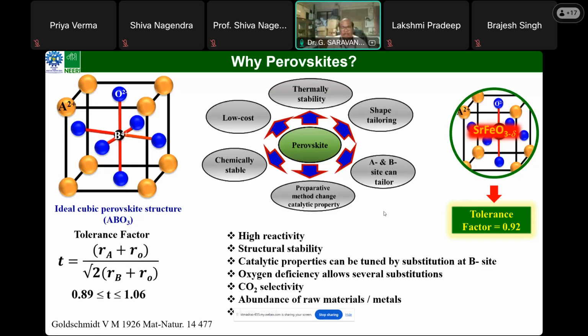to use perovskites for automobile exhaust applications, and it has quite some merit. It is quite stable because the phase formation temperature is generally above 800 degrees. You can play with the shape, you can tailor the A and B sites, and you can have scalability, and it is generally low cost. So there are a lot of merits. So we selected perovskites for diesel particulate matter oxidation.